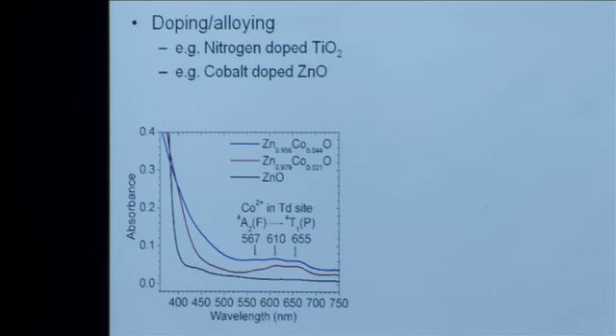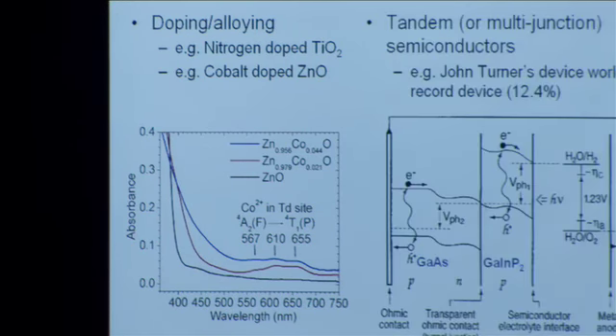What often happens, unfortunately, is by putting dopants into these lattices, you oftentimes kill the charge transport property. So yes, you excite many more electrons and holes than you otherwise did in the sun, but then these electrons and holes can't make it to the surface. They end up recombining at these defects, and you don't get that energy out of your system. So although there's been a lot of gains here, there haven't been as great as one could hope.